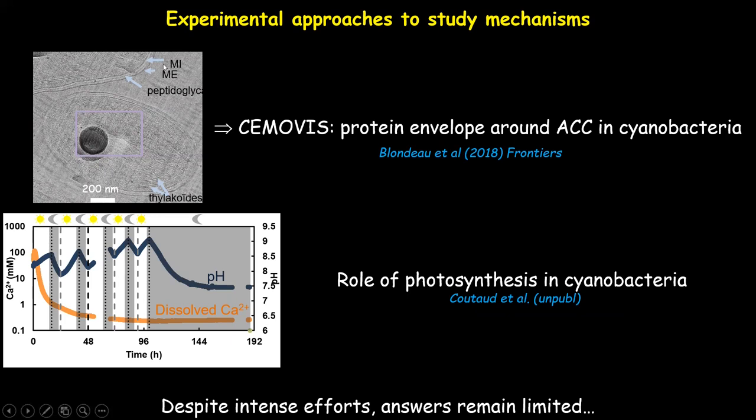time and energy consuming. We used cryo-electron microscopy to look at these carbonates. Here you see the globules of carbonates inside the cells. We needed cryo because if we use more standard electron microscopy or more standard sample preparation, those carbonates are just gone. We lose them. So we needed cryo. That was painful, but it worked pretty well, and we could observe some envelope around those carbonates. So they are formed within a compartment within the bacteria.